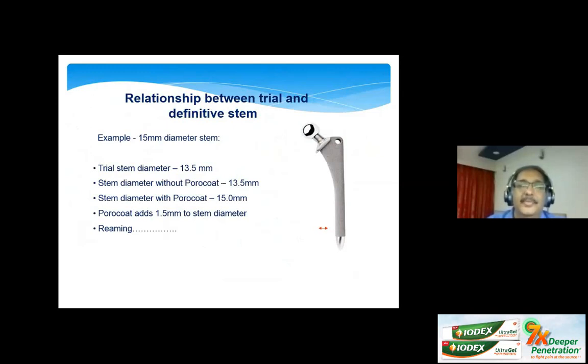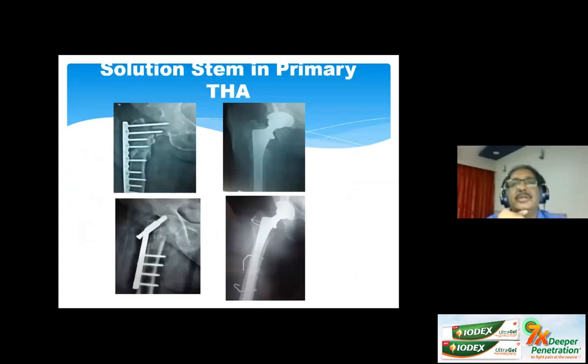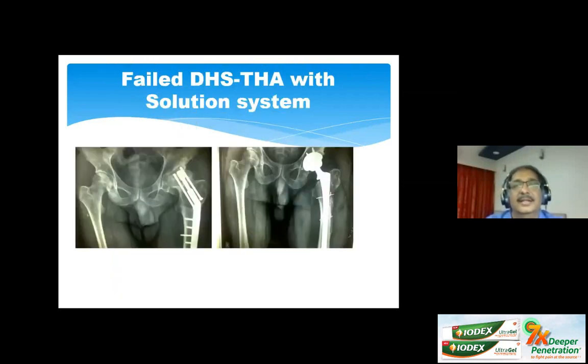So you have to be very careful because this is quite notorious to cause hidden cracks in the bone, and therefore reaming line to line of 0.5 mm more is recommended. Examples where I've used the Solution stem in a primary total hip is in cases where I've converted failed proximal femoral fractures, where you require a long stem to bypass the screw holes and get a good distal fit in the diaphyseal shaft. Another case where we use a Solution stem. In all cases where we have these screw holes, cementation is a little bit dodgy because we don't get adequate pressurization. And as Atul mentioned, if you do not get a good cement mantle, then the stem longevity is compromised.